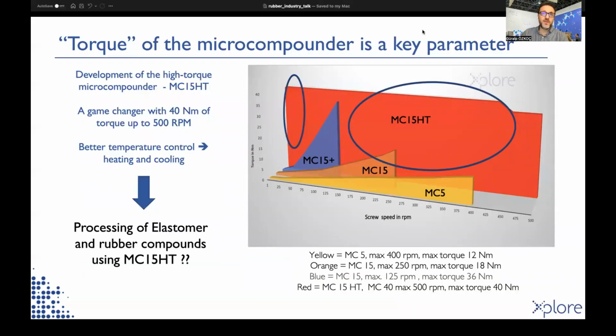The torque of a microcompounder is a key parameter to have successful mixing. In order to be in line with the current high viscous materials, Xplore developed a high torque microcompounder which has 40 Newton meters of torque per 15 cubic centimeter of melt. To be honest, at that time, this much of torque was more than enough for the processing of thermoplastics. But having such kind of an option made us to think if we could process rubbers in our new high torque microcompounder. Although we foresee some challenges already.